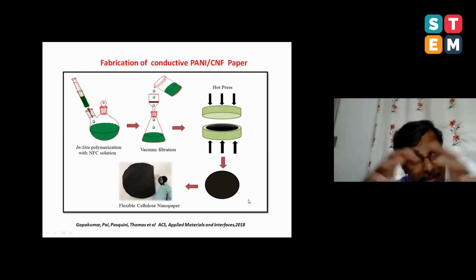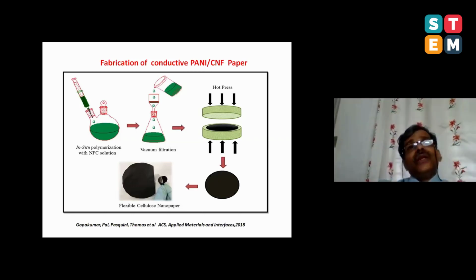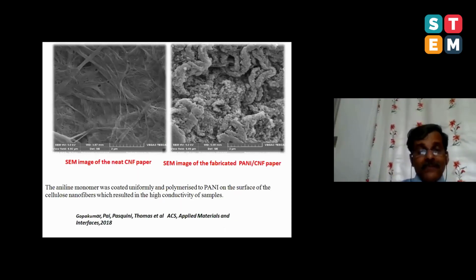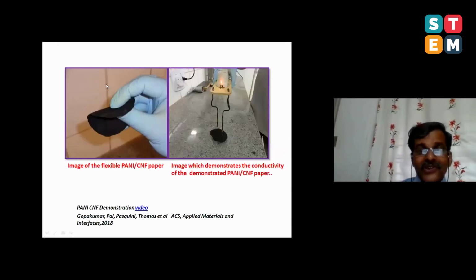And this is extremely conductive because we have in situ polymerized aniline on the surface of nanocellulose. Nanocellulose has a very high surface area. As a result of this, we got a conductive paper. This is the microstructure of this conductive paper. This is neat nanocellulose. And I will show you, this is extremely conductive. Dibu has proven it. This is a very nice conductive material. At the same time, it is flexible.